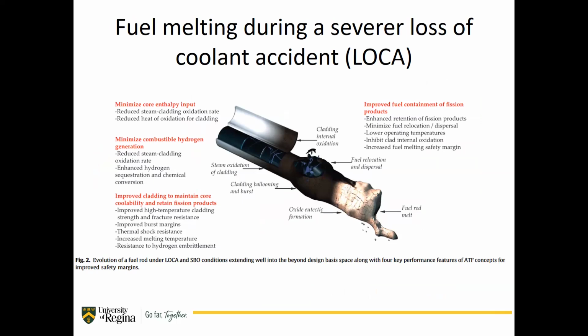This is a nice figure that's often used from a perspective article, looking at how the progress of the accident continues as time and temperature continue on. Initially, you're going to have your actual solid fuel, which is eventually going to start to crack as it heats up. You're going to start to have corrosion of the zircaloy. You'll then have this bursting of the actual zircaloy tube itself, so damaging of the actual fuel elements, followed by the formation of this oxide eutectic, and then followed by melting of the actual fuel into corium.